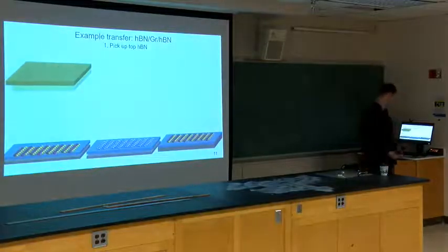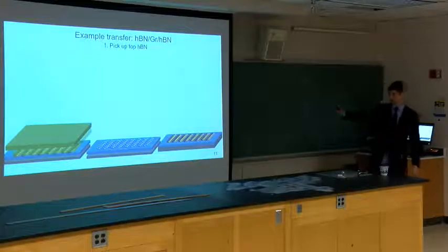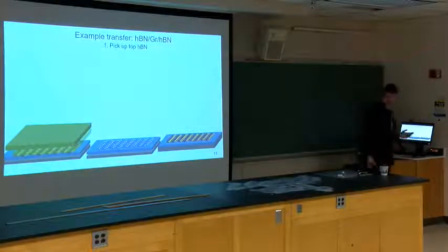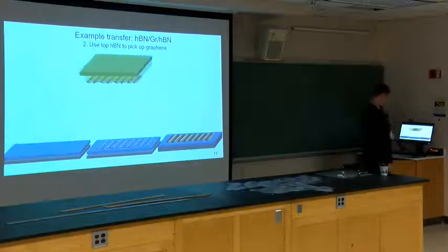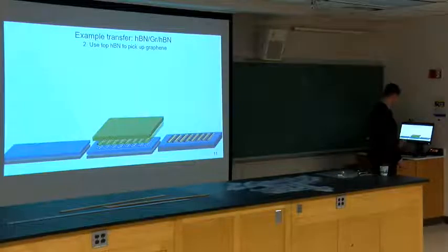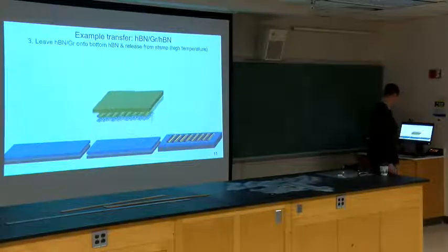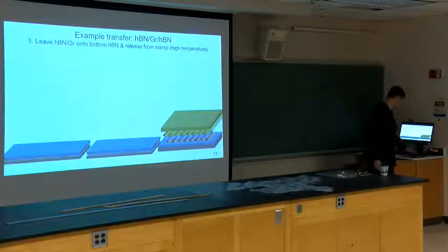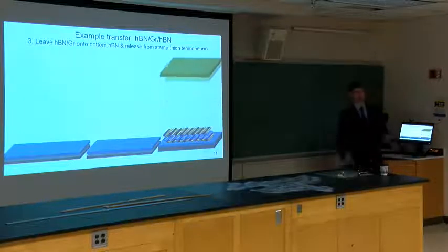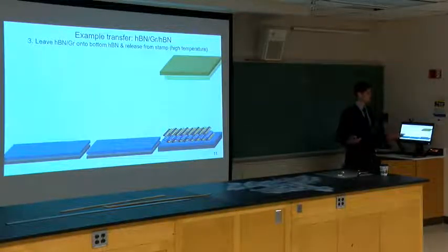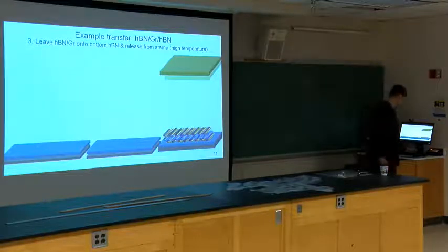So just a little demonstration, one example. We would take this glass slide, which is the green here, with a little polymer stamp on the bottom. We would pick up hBN, which is a great insulator, and graphene, pick that up, raise the temperature so we pass the glass transition temperature, and leave it on the substrate. Now we have essentially a perfect dielectric environment for the graphene, and we can have some fun with physics.